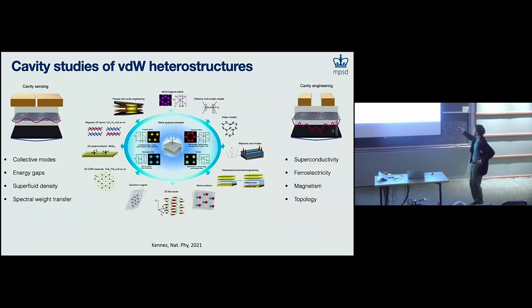But if you were to keep doing experiments the way that we're doing, where you have this patterned dielectric environment, you get this ultra-strong coupling regime, you could start doing experiments where you try to manipulate the ground state properties, and look at things like enhanced superconductivity and all these different things. And the way these experiments would work is you would do a DC transport measurement, similar to how Jerome is doing it. But then if you see something different, you could then do on-chip terahertz spectroscopy to see how the modes are coupling in the background, how energy is flowing, and this could give you a hint if it's cavity physics or something else causing the change.